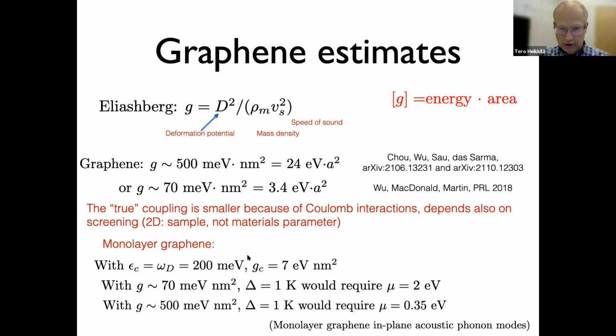But then you can assume that you dope the graphene and try to get it superconducting. Just making estimates of how large a doping you would need to get a delta equivalent to 1 Kelvin, the TC would then be a bit less. If you assume this smaller coupling value, you would require doping which is almost the size of the conduction band in graphene. So this is not that easy to realize. This basically states that monolayer graphene is not a superconductor, at least not very easily, which was already known in the literature before.